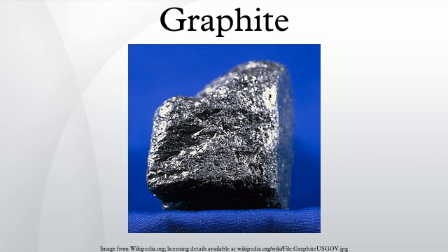Electrodes. Graphite electrodes carry the electricity that melts scrap iron and steel in electric arc furnaces, which are the vast majority of steel furnaces. They are made from petroleum coke after it is mixed with coal tar pitch. They are then extruded and shaped, baked to carbonize the binder, and finally graphitized by heating it to temperatures approaching 3,000 degrees Celsius, at which the carbon atoms arrange into graphite. They can vary in size up to 11 ft long and 30 inches in diameter.